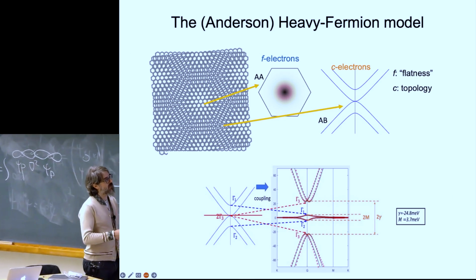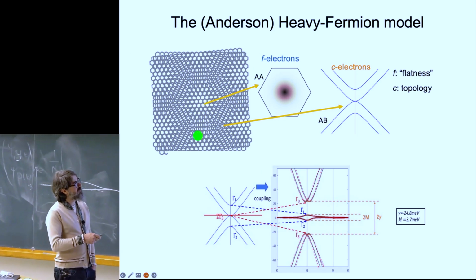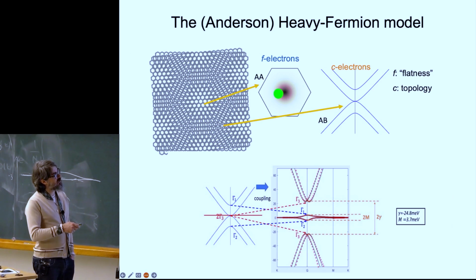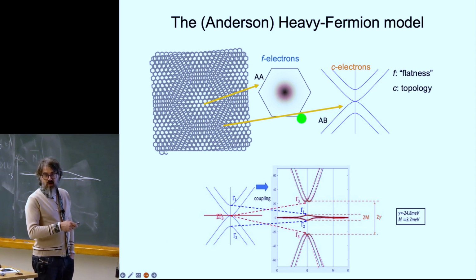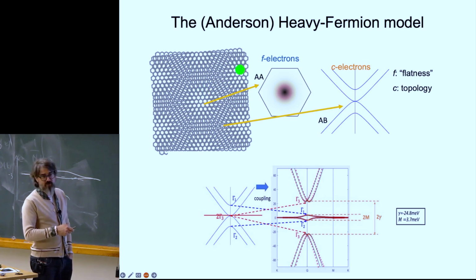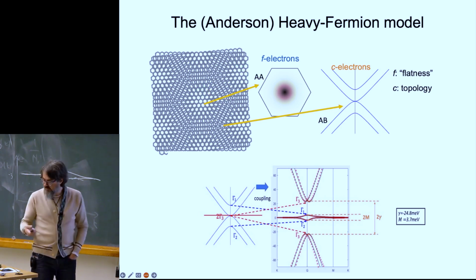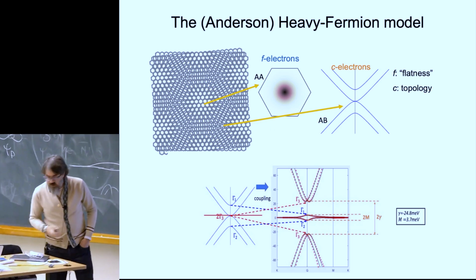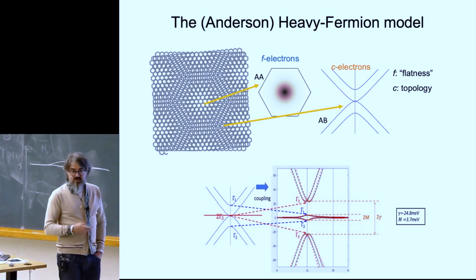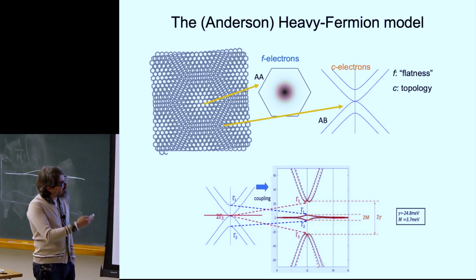We can build Wannier orbitals. This is by doing Wannier90, you can get some localization. It's 0.2 of the unit cell. In fact, there's zero hopping between these two F orbitals, by abuse of language. Between here and here, there's zero hopping. So these are just localized orbitals. But we know there's superconductivity, etc. This system cannot be made out of localized orbitals. So there's got to be a chain, there's got to be some delocalized state.